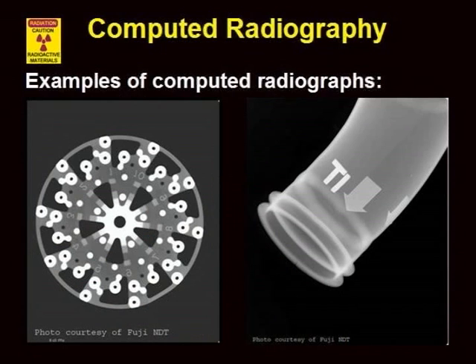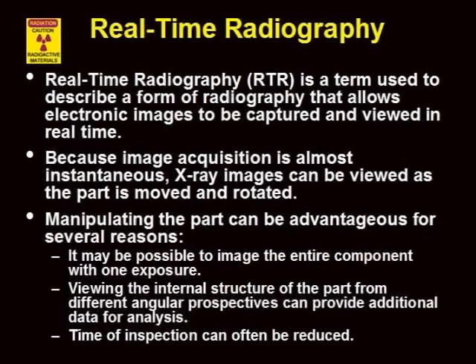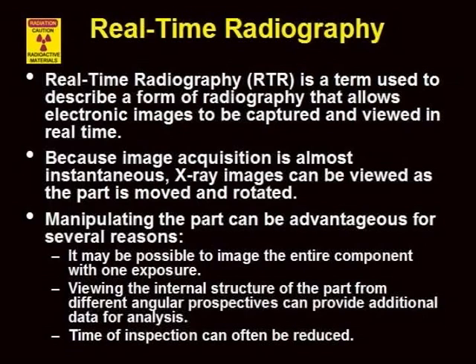This slide shows some computed radiographs. Real-time radiography permits electronic images to be captured and viewed in real-time. The image may be viewed as the test article is moved and rotated. Remember that cracks can be difficult to detect unless viewed from the optimum perspective. The real-time approach permits the entire test article to be inspected from many different perspectives. If a special x-ray generator with a small effective spot size is used, the test article may also be moved towards the source and away from the detector to magnify the image. Magnification on the order of 100 times can be achieved with the proper point source of x-rays. Compared to film radiography, real-time radiography can be performed in a shorter amount of time.